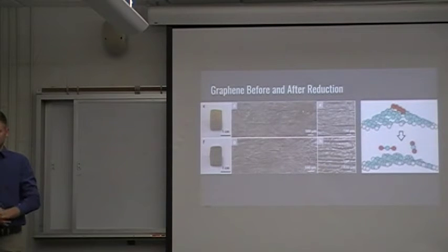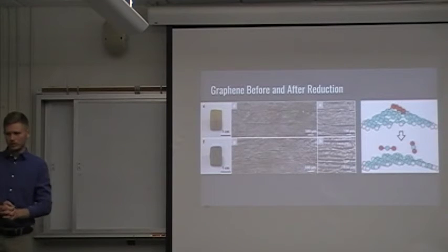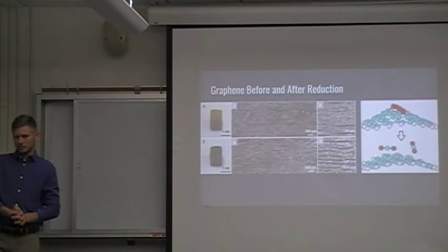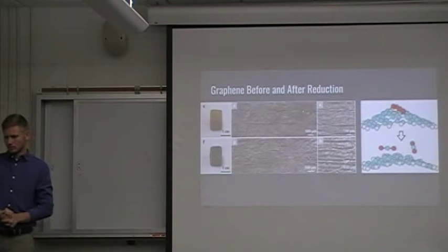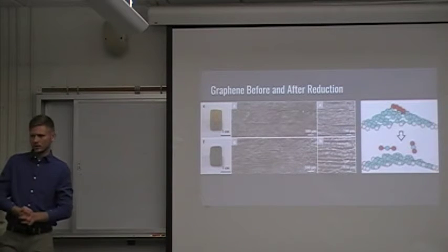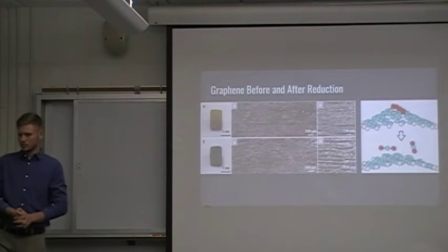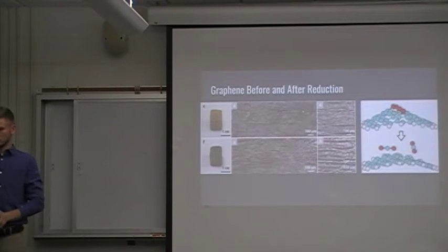Right. The hydrogen is going to go in and rip off the oxygens. So what you're going to get is water. It would seem like that's what I would have thought too, but that slide suggests otherwise. The hydrogens go in as 0, and they get oxidized to +1 with the water. And then the carbon would bind to itself again? The oxygen gets pulled off of the carbon, and the oxygen stays -2 the whole time. As the hydrogen pulls the oxygen off, the carbon is reduced back down to 0 because it doesn't have the oxygen in it anymore. So the hydrogen is being oxidized, the carbon is being reduced, and it's happening by stealing oxygen. So then the carbon has that open spot to be double bonded to another carbon.